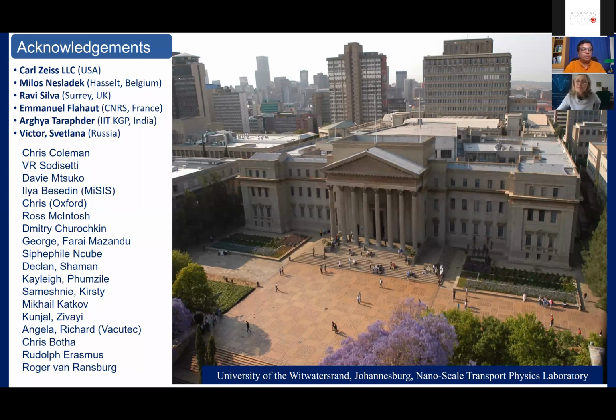I have not shown some of the slides. I have to go back. So the details are written there. But what is important is that in the processing, you can change the size of the grain of diamond or nanodiamond, which varies from 40 nanometer to 100 nanometer. So that is the range basically. So it was done very carefully.